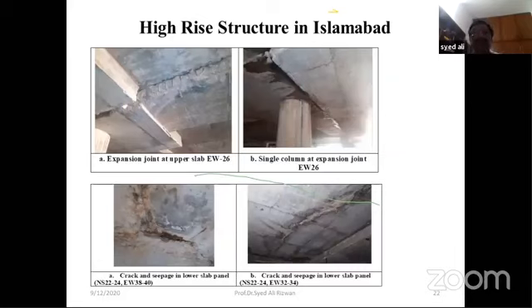Then another case of a high-rise structure in Islamabad, you can see these beams were quite huge. They were projecting beyond the slab by 9 inches. And if we consider a 9 inches slab thickness, the overall beam depth will be 18 inches, and this lateral dimension was around 5 feet. This girder column to column spacing was around 35 feet in both the directions.